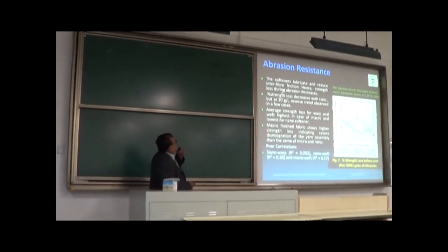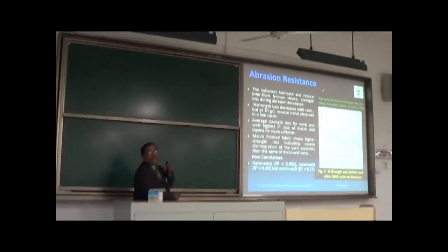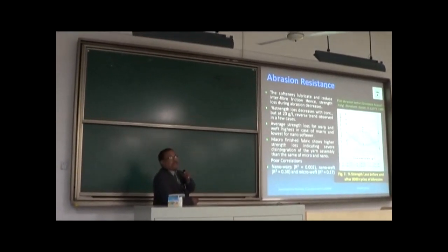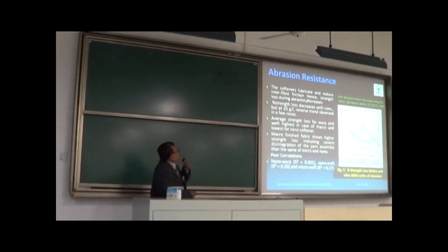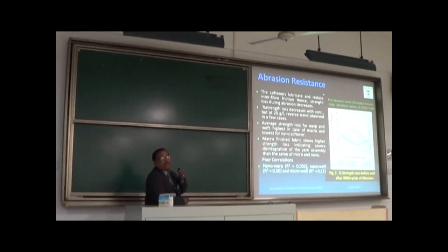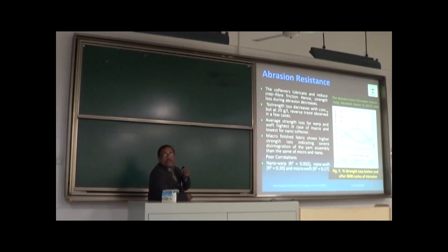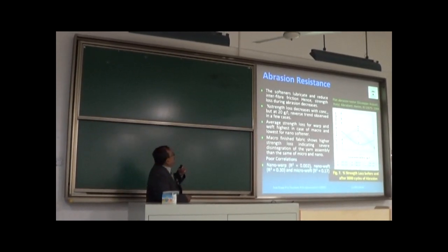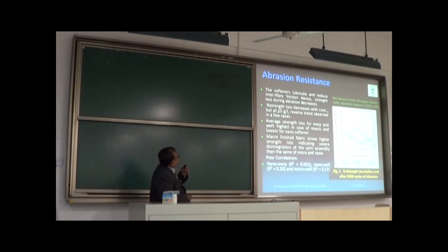Then abrasion resistance. Softener lubricates and reduces interfiber friction, hence strength loss during abrasion decreases. More softener means less loss in abrasion resistance. Strength loss during abrasion.